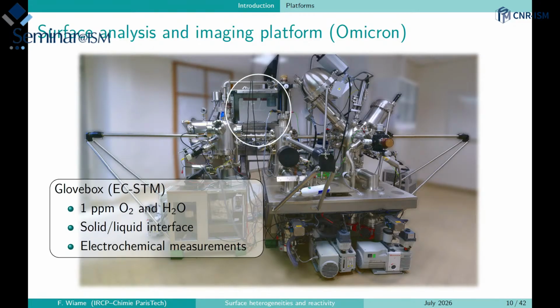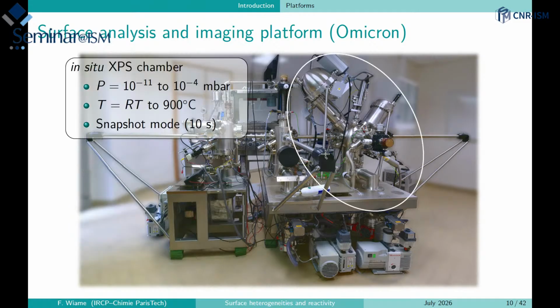And again, a glove box connected for electrochemical measurement. And then in the second main chamber, the first analysis chamber, we have an in situ XPS where we can expose while we are doing the measurement up to a pressure of 10^-4 millibar, thanks to a differentially pumped reaction cell. And also at temperature varying from room temperature to 900 degrees Celsius.